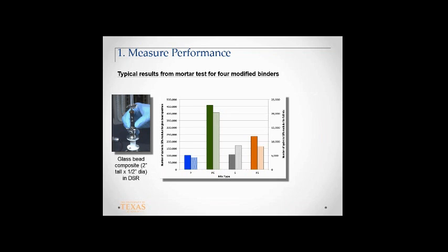Just to give you an example of how some of these things are being used, this is a result from using the glass bead composite. There, each one of these pairs represents a different binder. And these binders are interesting because all four of these binders are exactly the same true continuous grade within half a degree to 1 degree. So I forget the exact grade, but they're all on the high side 67 plus or minus half a degree. On the low side, they're all negative 25 plus or minus half a degree.